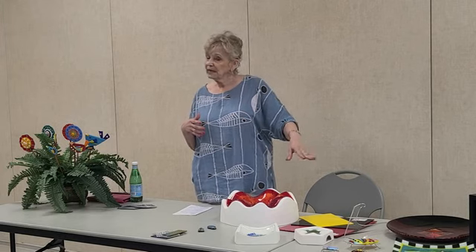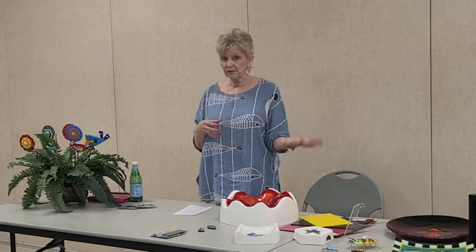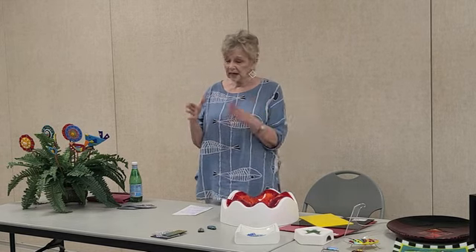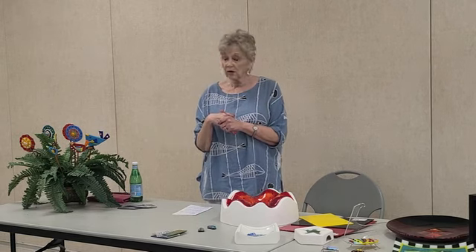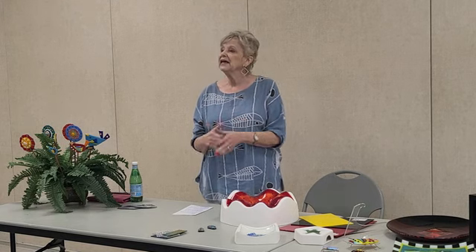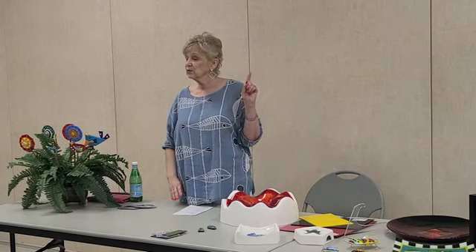Depending on how thick it is, how big it is, how many layers it has, all kinds of things go into how long you hold it at that temperature. The glass I use is called System 96, and I'll explain that in just a second. You have to hold it at 950 degrees, and then you determine how long. For that one, because I didn't want it to come apart and I had worked really hard on it, I probably held it for 3 hours. Then you can slowly start cooling it down, but you have to get all your little children back in line before you can let that go. That was the hardest thing for me.